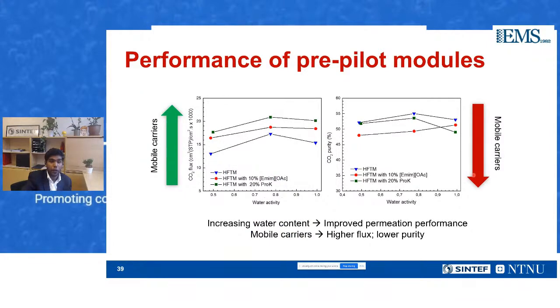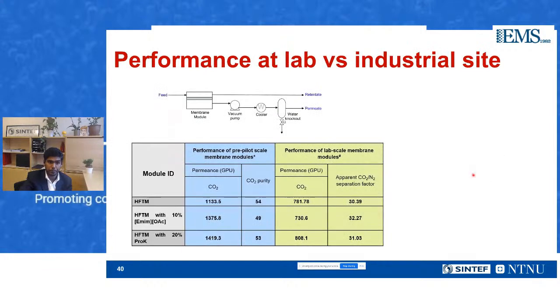So in the field, we found out that the membranes perform quite well. The upscale membrane modules perform quite well, where the CO2 flux was a function of water activity, which was quite evident because of the facilitated transport membranes. And the purity was up to 50 to 55% at the conditions that we tested. That was quite expected of the membranes in single stage operation. And we also found that the mobile carriers increased the permeance and lowered purity a bit.